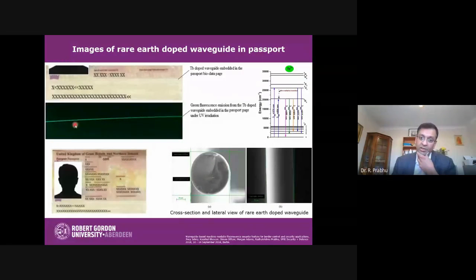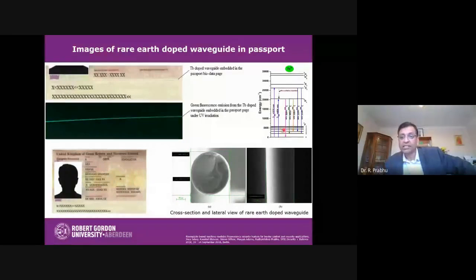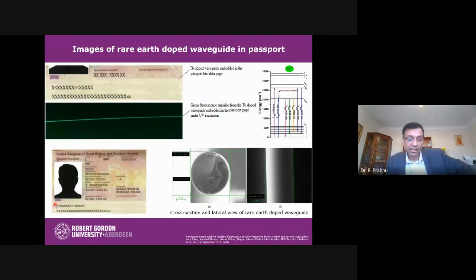Around 25 micron fiber, which is a glass fiber doped with a rare earth element called terbium. And terbium has strong emission if we illuminate with UV light. This was emitting a green emission, and this is a strong and sharp emission. And that can be used as a security feature inside the passport or data page. You can see this is the typical data page inside which we integrated the optical fiber. And optical fiber is not clearly visible here. You can see this is a tiny reflection here. But if you illuminate under the UV light, it's very clear. It's emitting a green line.